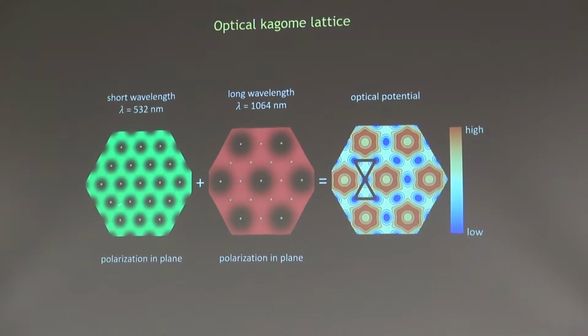We can create, let's say, this pattern produced by the intersection of the 3 green-colored beams in that diagram. So I take 3 beams intersecting at 120 degrees. I make sure the polarization is in plane for this particular situation. Then the intensity pattern of light that's produced inside of the cell looks like this. It has a triangular lattice of locations where the intensity goes to 0. And for the atoms we're working with, the green light acts as a little bit of a repulsive potential. So the atoms end up being localized at the positions where the green light is dark. So that creates a standard triangular lattice in 2 dimensions.